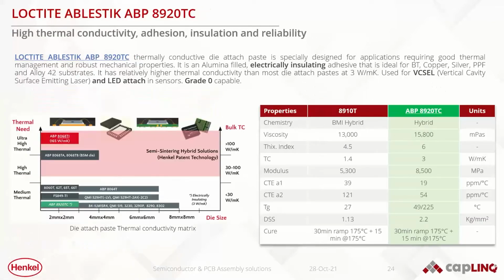The 8920TC, on the other hand, is a thermally conductive, but electrically insulating material. Thermal conductivity is always relative, and this one has a thermal conductivity of 3 watts per meter Kelvin, which is relatively high for an electrically insulating die attach material. For automotive applications, it has been used for grade 0 reliability and applications such as vertical cavity lasers and LED attach in sensors.